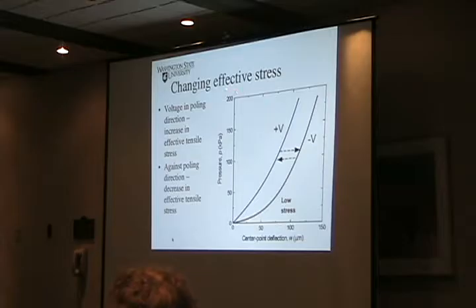And so we should be able to change the effective stress by changing the charge on the membrane. So what we do is we go ahead and we can test an open circuit or closed circuit. And if we apply a positive bias to the membrane, it looks stiffer than if we apply a negative bias. And again, Moralt had done this where they did small deflection measurements and found increases in efficiency with that. We're just moving out, so instead of moving about 5 microns, we're going to just push it out about 100 to 150 microns and alter the residual stress in a pressure deflection